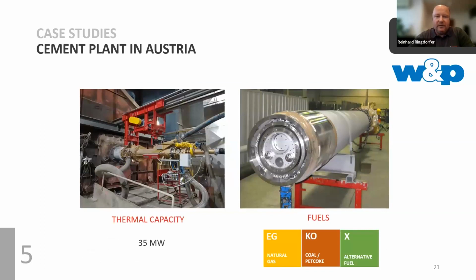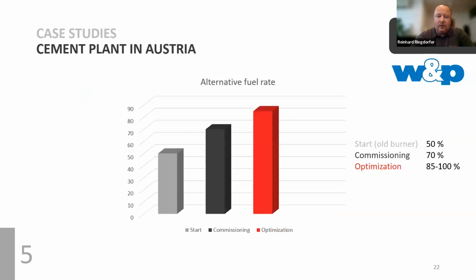So here you can see the installation and the burner. It's, as I said, a small burner, 35 megawatts, where the primary fuel is mainly coal and petcoke. Natural gas is used for heating of the burner, and we have one channel with a solid secondary fuel, which you can see here, with the pneumodeflector nozzle. And as I said before, material was very well prepared. And if I say very well prepared, we're talking about less than 5% moisture and a very fine material.